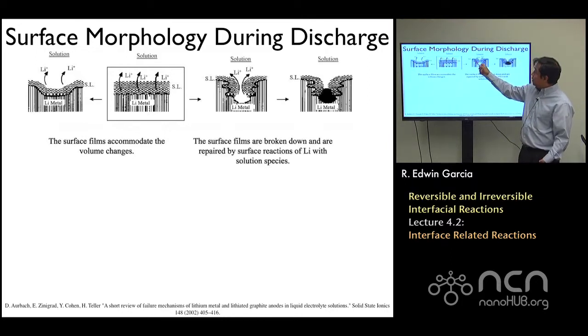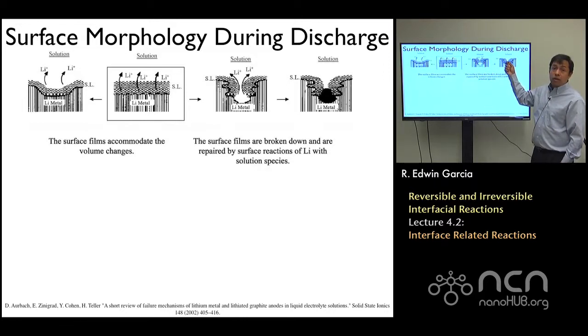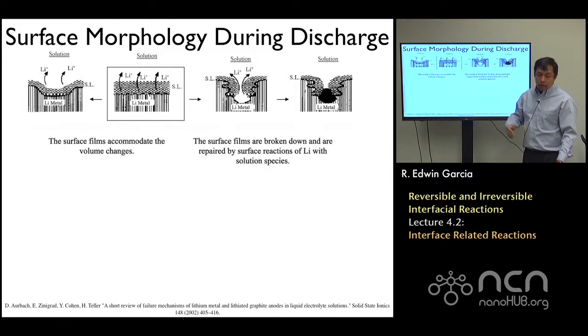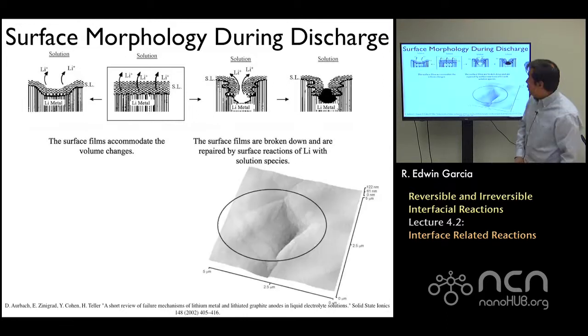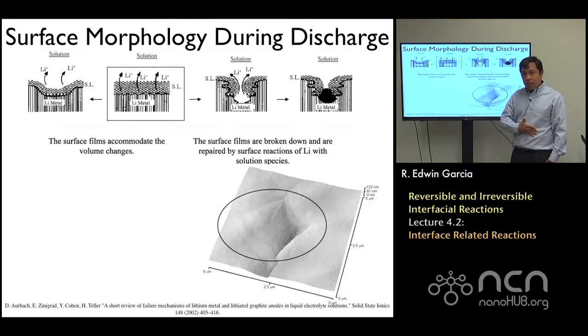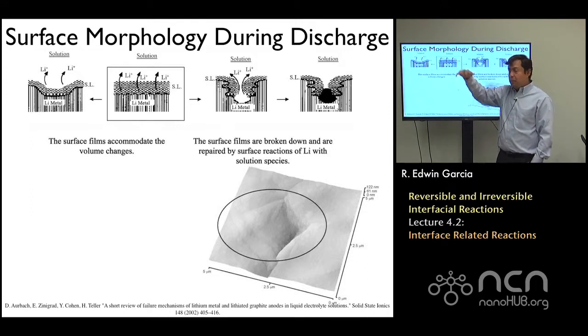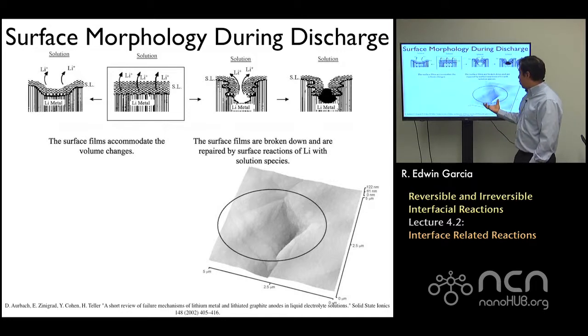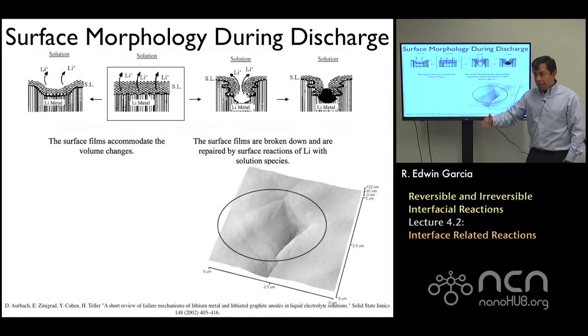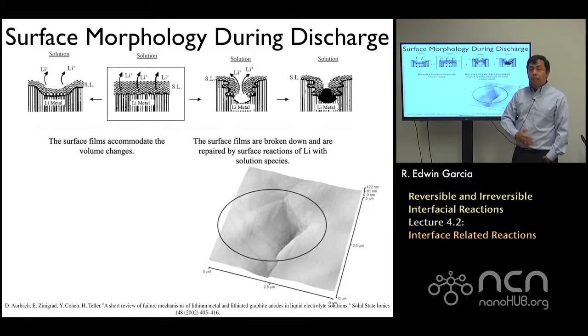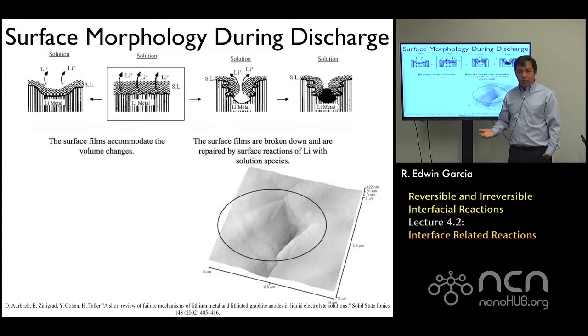As a result, you can develop pinching or other regions with other reactants that you really don't want there. Experimentally, it's observed that you will have these valleys, and so after several charge-discharge cycles, some regions will have these giant buildups of lithium accumulated, while in other regions you will have these giant valleys or depressions, completely changing the efficiency of the reaction, which is also detrimental for the performance of the cell.